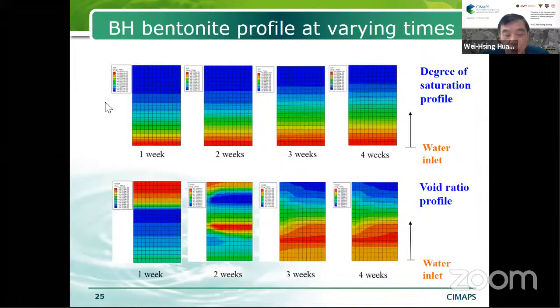So this figure shows the detailed degree of saturation profile and void ratio profile here. It is noted that the lower part of the specimen swells upon the uptake of water, while the upper part becomes dense under the swelling pressure from the lower portion.